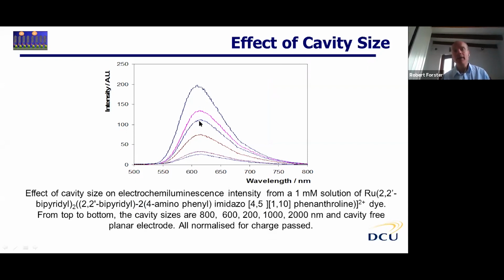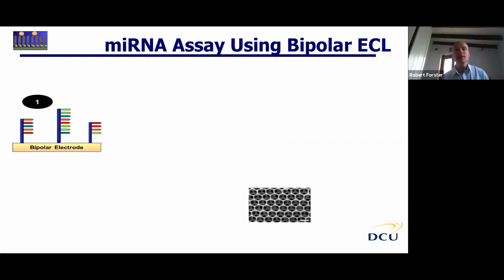Smaller, 200 nanometers, is not necessarily better. 800 nanometers actually represents the most intense emission. And these are corrected for the charge passed, which really reflects the efficiency of the ECL response.